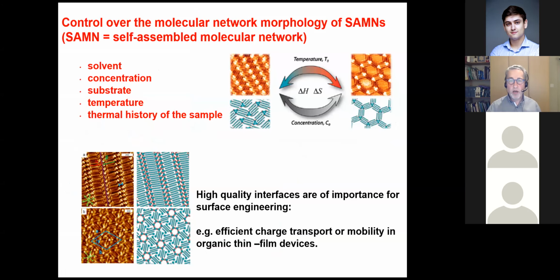And this is only one of the many systems we and others have investigated. And what we have learned is that by controlling solvent, concentration, substrate, temperature, sometimes the thermal history of the sample, we can have some control, or quite good control even, on the organization of these molecular systems on the surfaces. Such systems we call self-assembled molecular networks. Now, of course, you will probably think, well, beauty, that's nice, but what about function? Well, the system I have introduced to you, the 4-component system, is not functional at all.